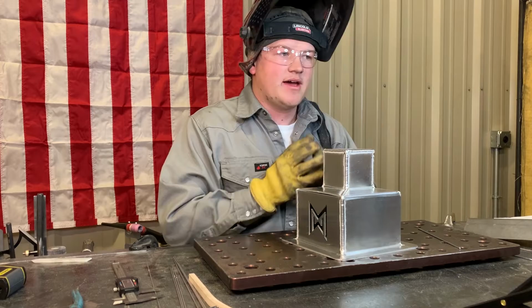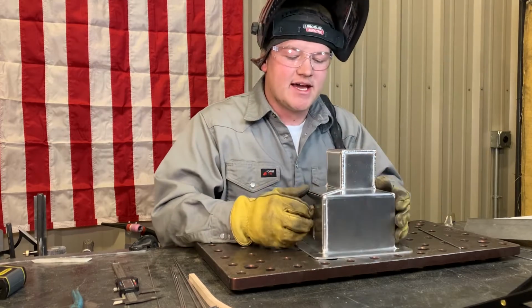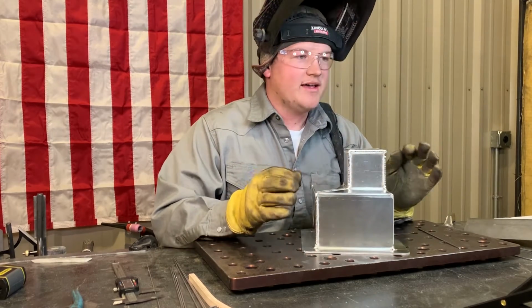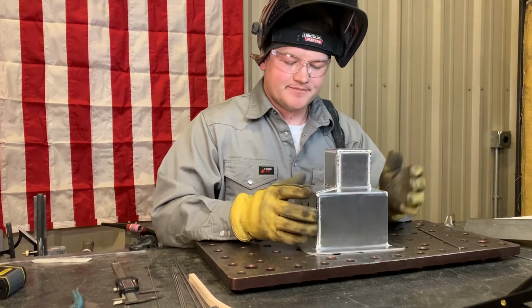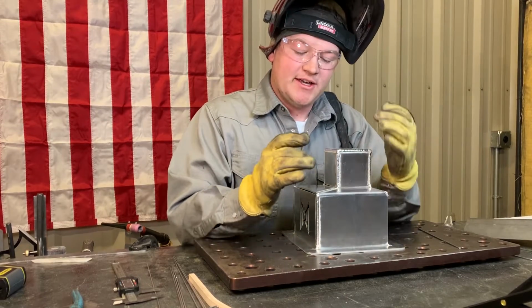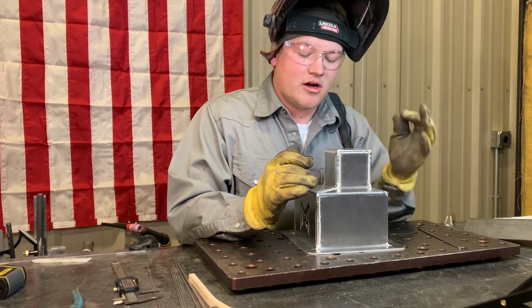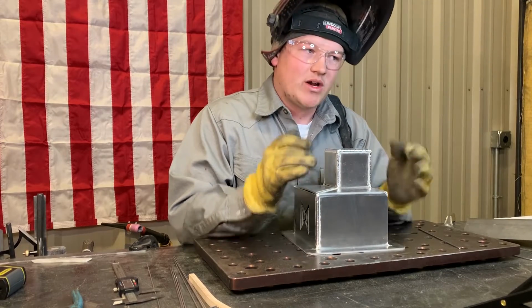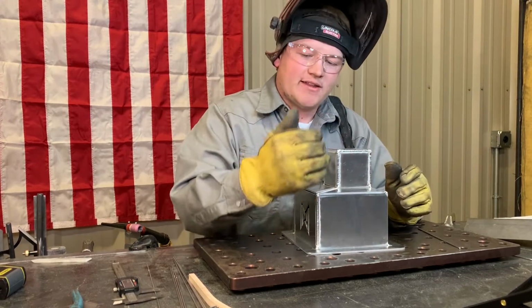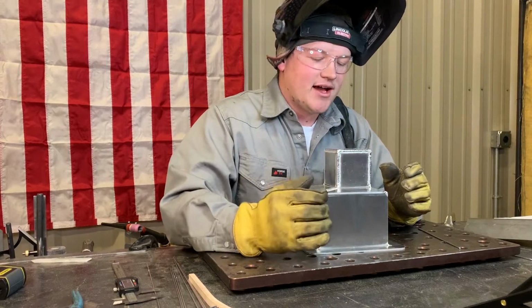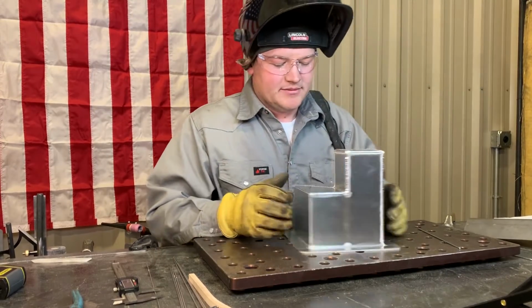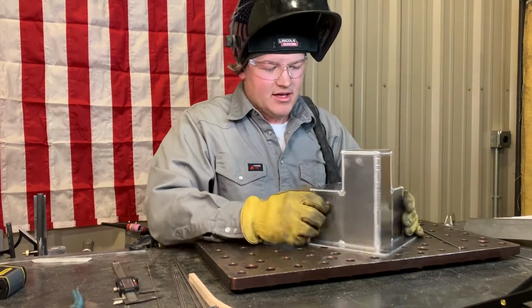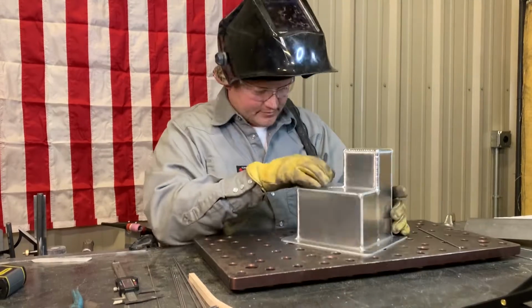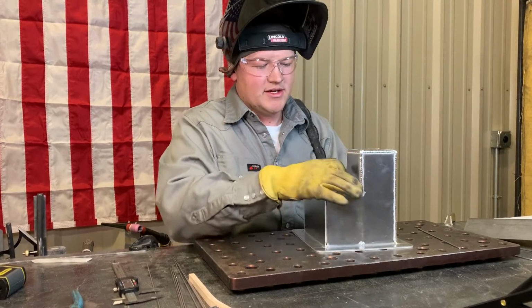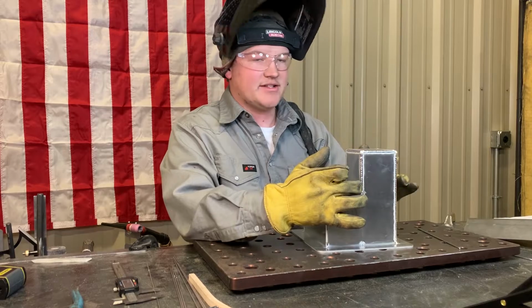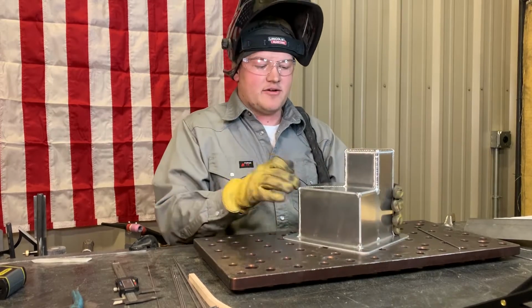With this thin a sheet metal, it definitely should be penetrating on the backside. The best way I like to know that I'm getting full penetration is when I start my weld puddle, I'll add a little bit of filler wire, and when I watch it droop down, I know that weld metal has sagged into that weld joint and I'm good to go. So now that one's welded, I'm going to weld these two fillet welds so I can cover up my stop and start with this bead around here.